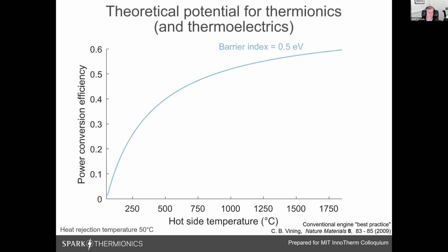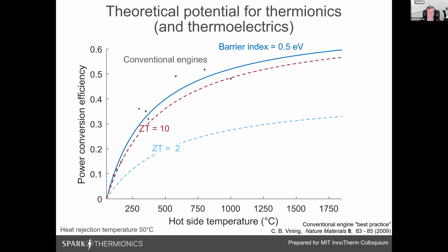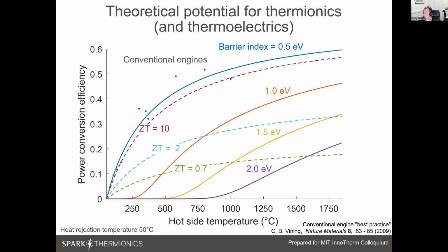And I'll be spending a couple of slides now describing what the opportunities within this are. So you can essentially just write down what is the possible efficiency of a thermionic device as a function of temperature, parameterized by this barrier index. And the historical folks were typically at barrier indices around 2 eV. However, that was, as we'll describe, part of the limitations of the technology of the day. It's quite straightforward to create a work function around 1.5 in an operating device, and in a vacuum chamber, it's very easy to get down below 1, and I'll highlight some of those as well.